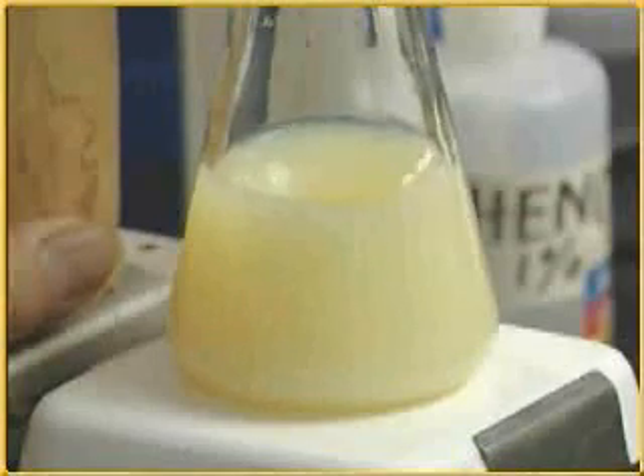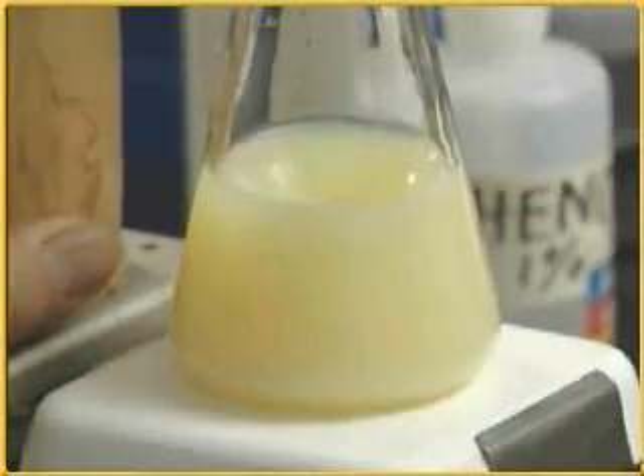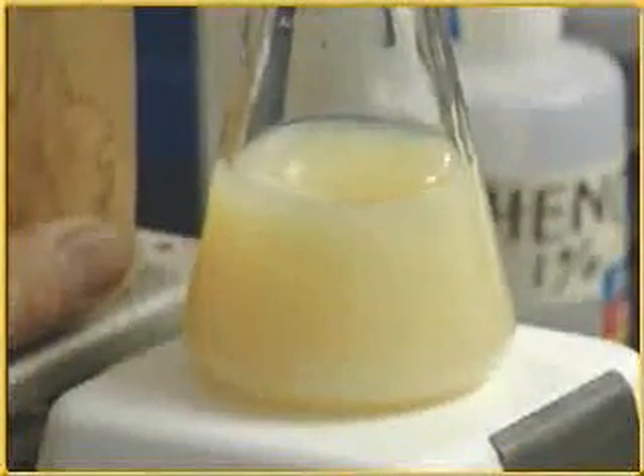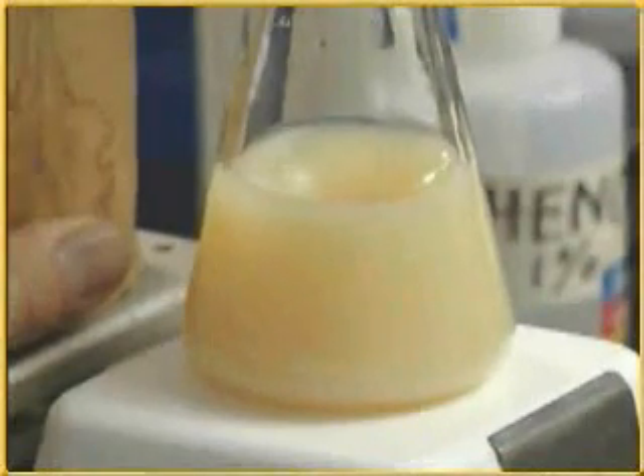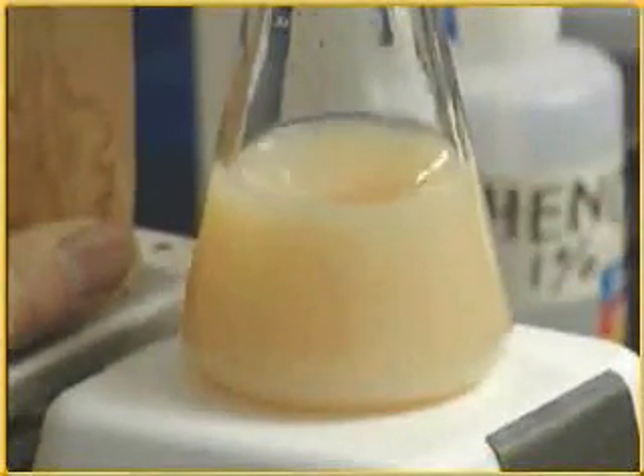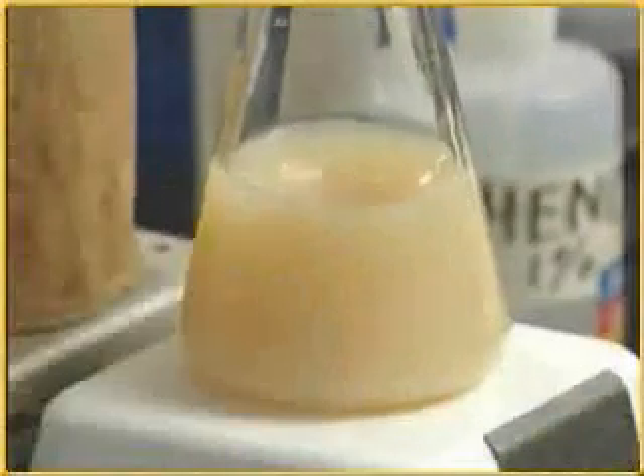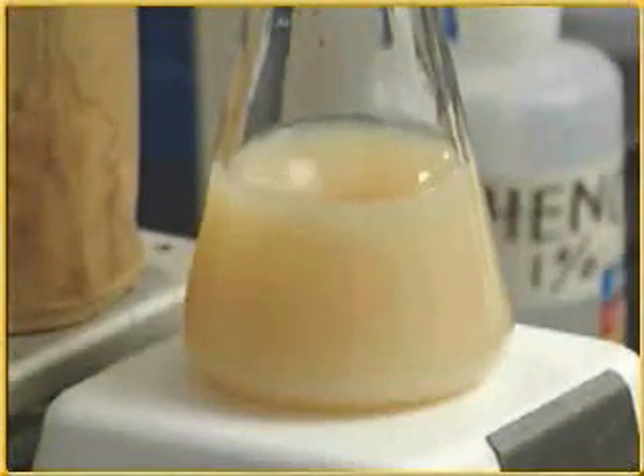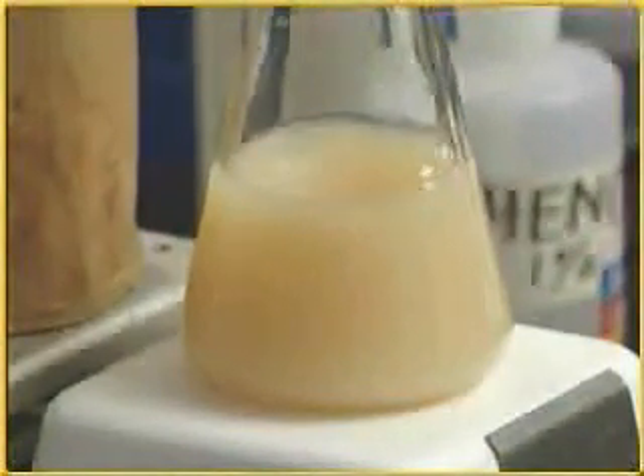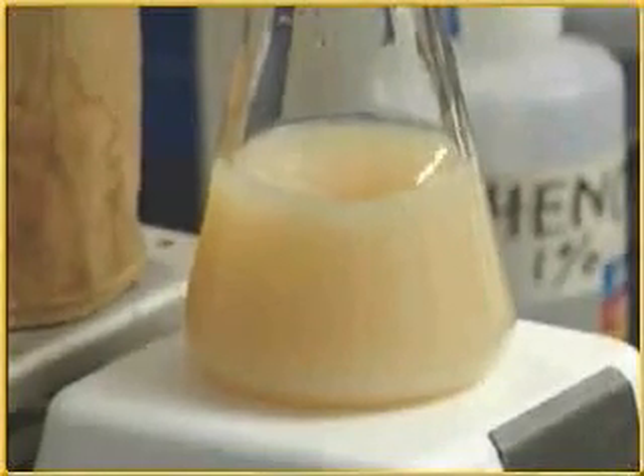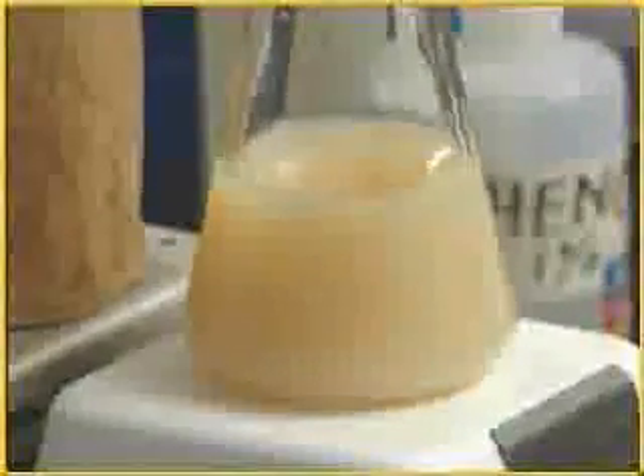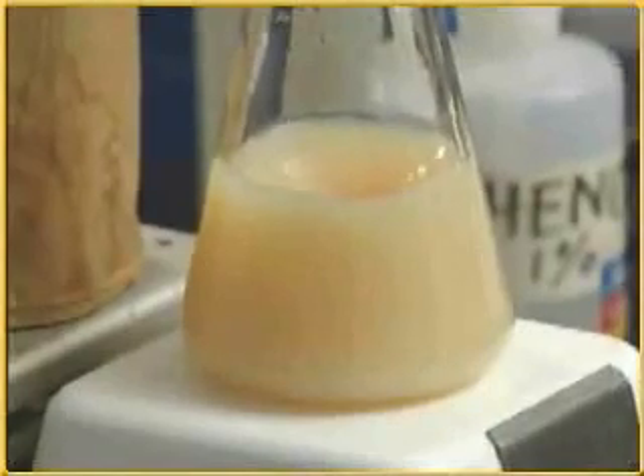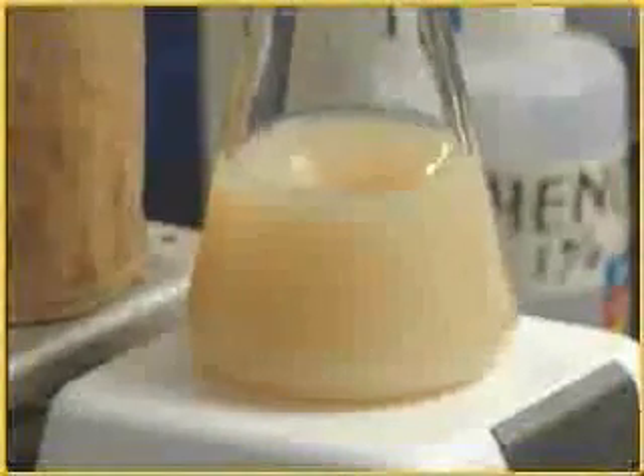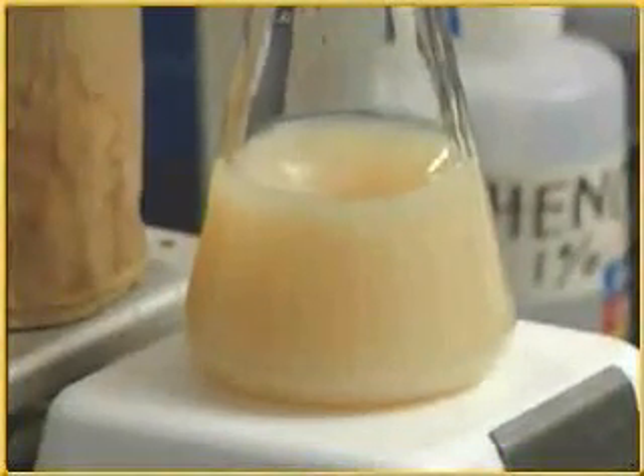The chloride level in a phosphate bath is often overlooked. When a bath's chloride level gets too high, typically above 100 parts per million, corrosion can occur. This genie cannot be put back in the bottle. No rust preventative or additive will prevent corrosion from occurring once the chloride levels are too high. There is no alternative but to dump the bath. The tank should then be rinsed to remove any excess chloride. The rinse tanks should be dumped as well.